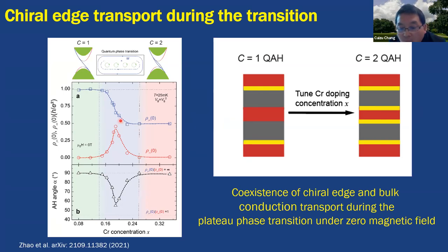But we know that in the quantum anomalous Hall field, we usually use this ratio to determine if the quantum anomalous Hall state is surviving or not. So here, because the ratio is always greater than one, we can see that during the transition regime, the original chiral edge transport always persisted. And in this regime, the chiral edge transport and the bulk transport coexisted during this plateau phase transition.